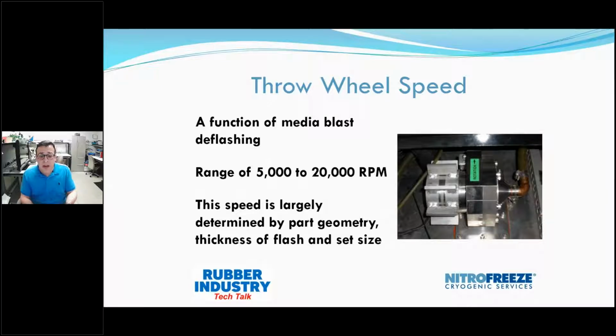What I've found is that at the very high end of the spectrum, if you were running near 20,000 RPM, there is the opportunity, and it's not a good one, to remove flash but also start to chip away at the part. That's something you want to avoid. So it's always good to start in the middle, and you can get more aggressive as you go, adding say 1,000 RPM as you go. That's what I would recommend.